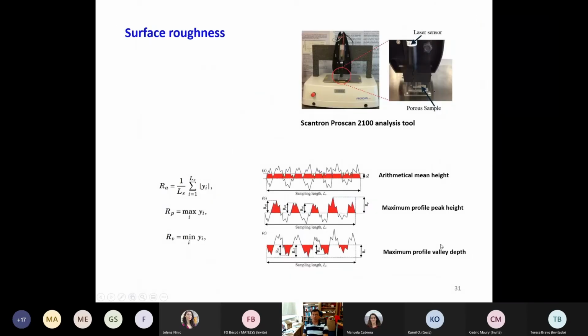As I mentioned earlier, surface roughness is also very important for us. So we use this Scantron Proscan 2100, which is basically a laser scanning device to measure the roughness. What it does is scan the surface fluctuations, and we take a statistical average of that, and that is the Ra factor, the roughness factor that we need for defining the roughness of the surface.